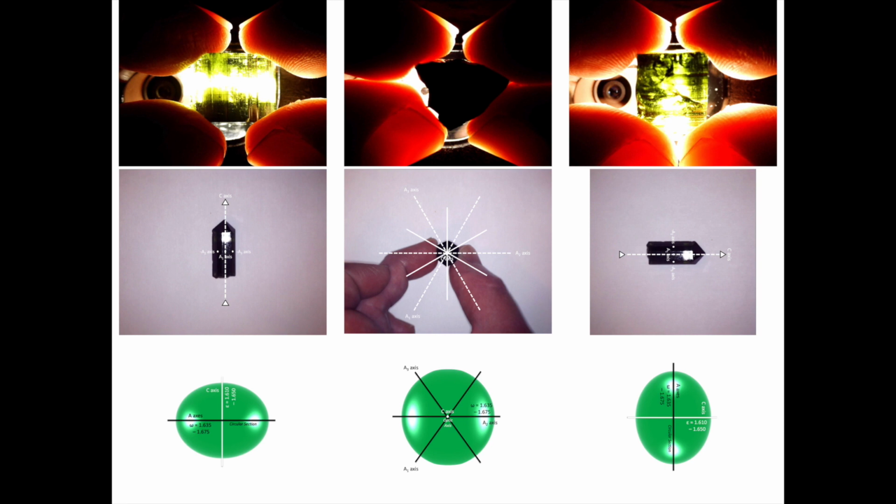As I mentioned before, the pleochroism of our tourmaline is actually pretty extreme. We get into a unique situation with our tourmaline when viewing it with normal light. Because omega is associated with almost complete absorption of light, the deep green color that we observe is almost entirely associated with refractive index epsilon in this case. Our tourmaline is actually acting as a linear polarizer. So for more on that, check out the video Snellius Minerals Linear Polarizers.